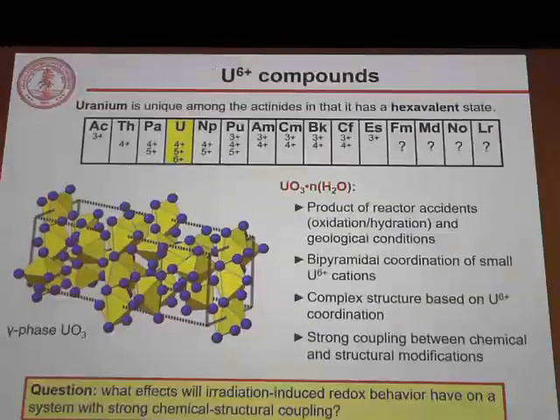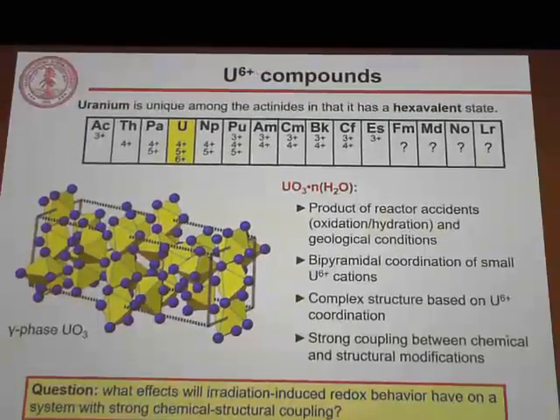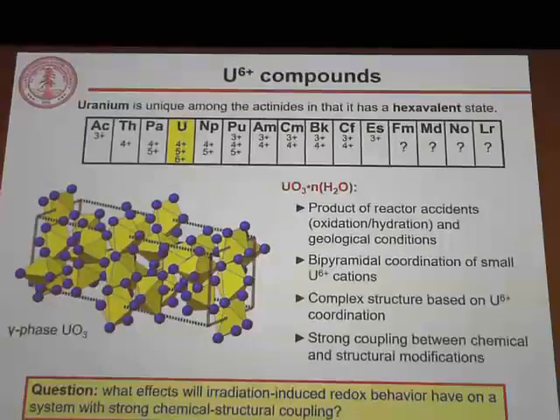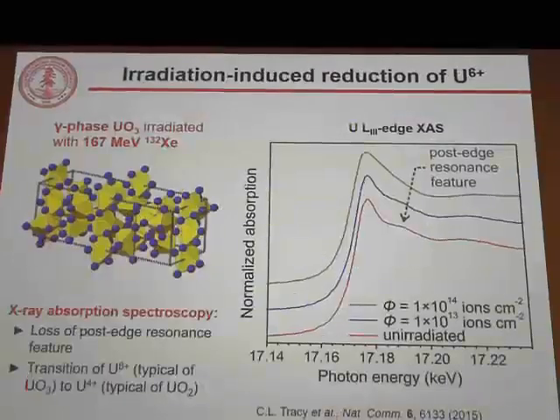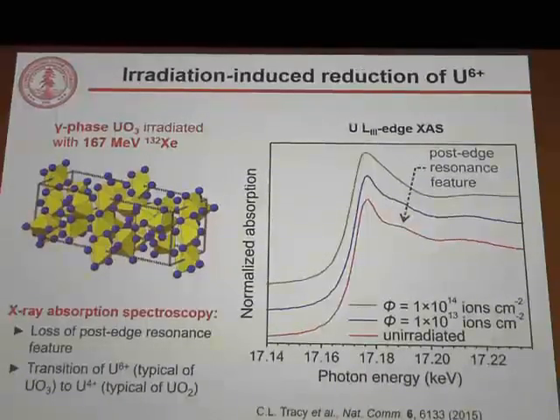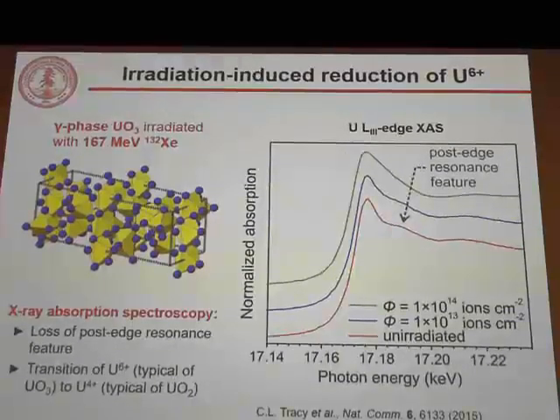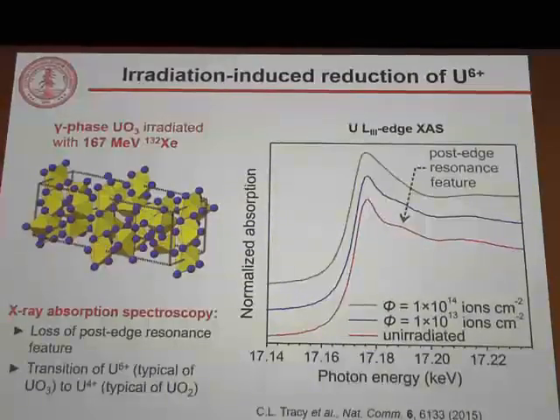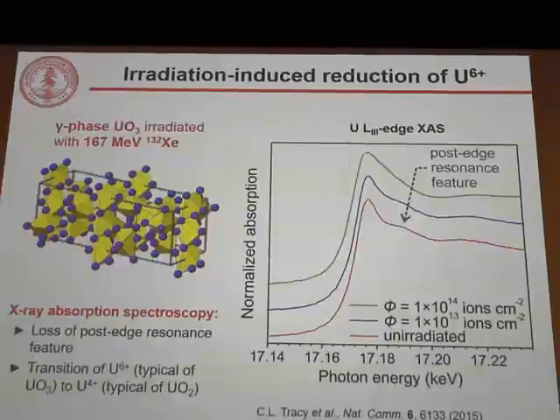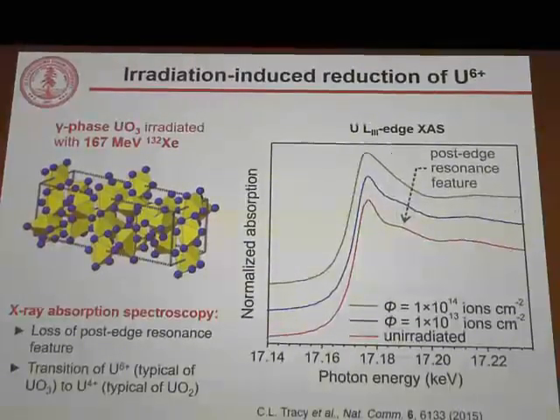What happens if we reduce hexavalent uranium to lower oxidation states? Will these structures be dramatically modified due to the structure-chemistry coupling? If we irradiate these materials and characterize the chemistry using X-ray absorption spectroscopy, we see that following irradiation, we have the loss of this post-edge resonance feature, indicating the loss of hexavalent uranium and a transition to tetravalent uranium, as would be found in uranium dioxide.